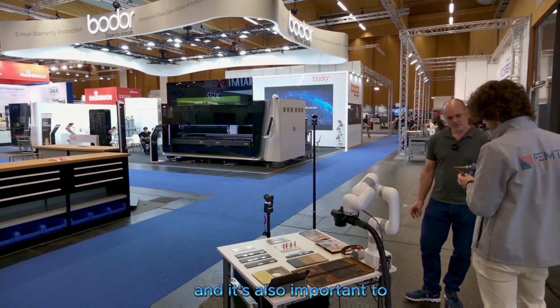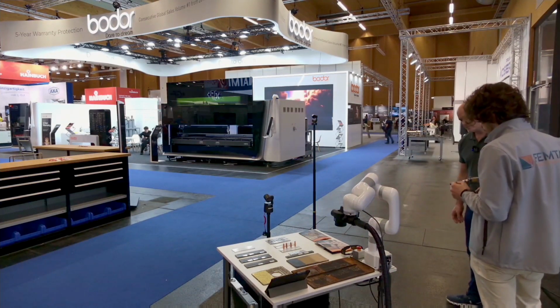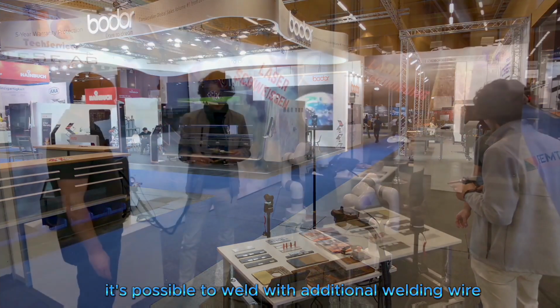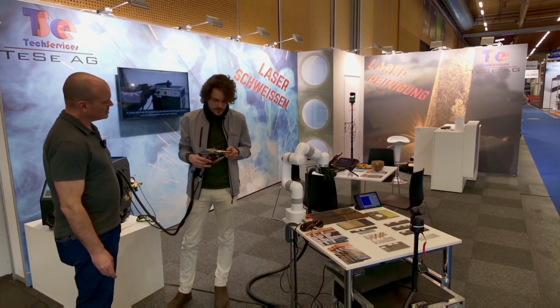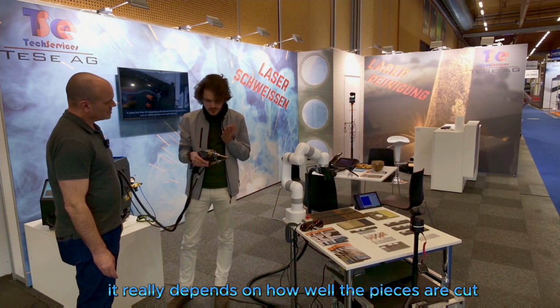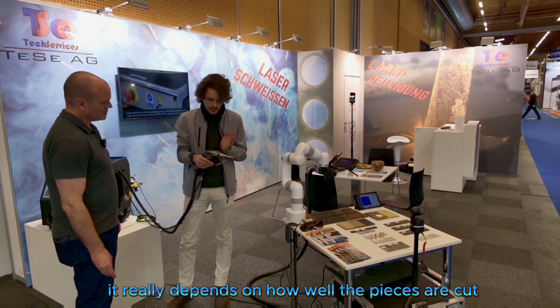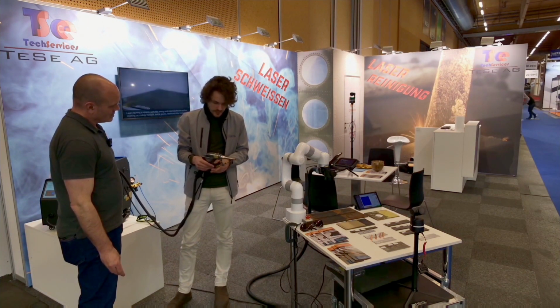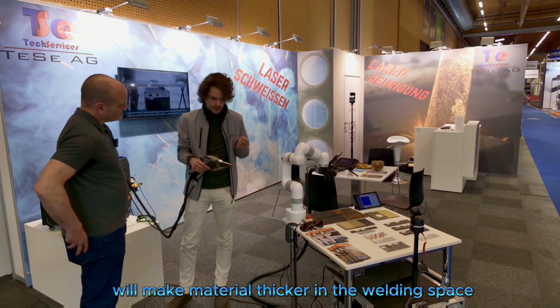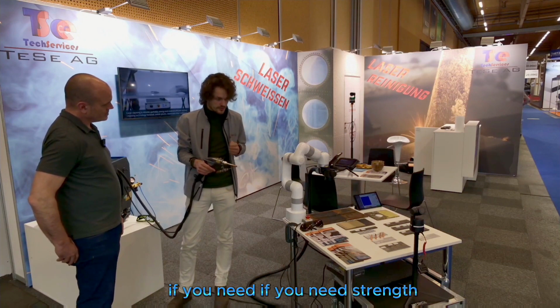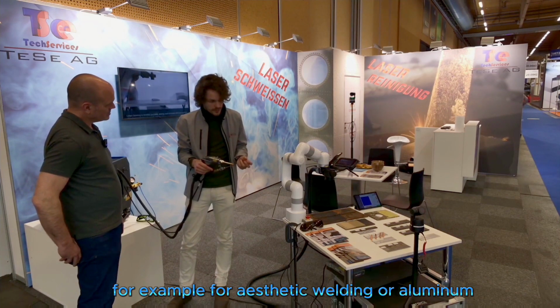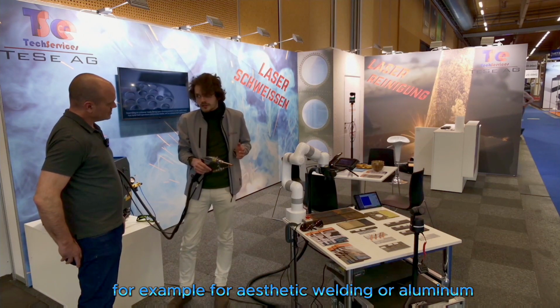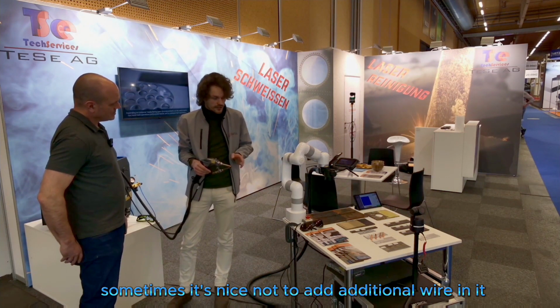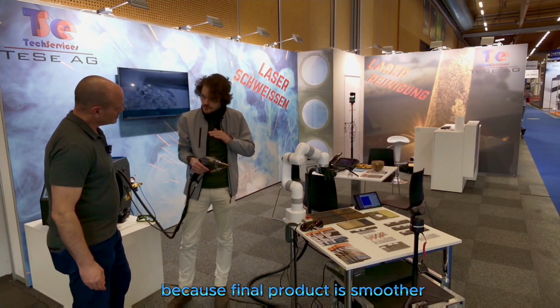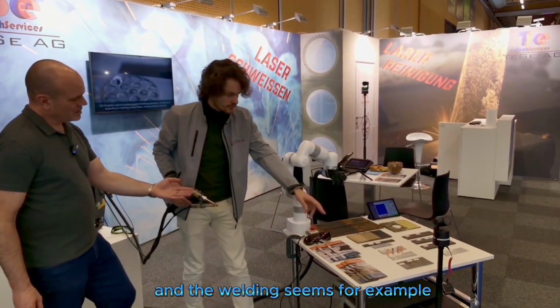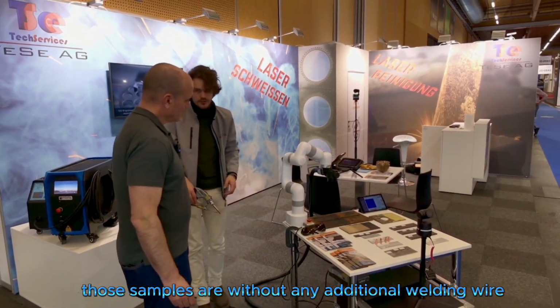And it's also important to say that it's possible to weld with additional welding wire, but also without additional welding wire. And the results sometimes can be better with or without. It really depends on how well the pieces are cut and how well they fit. In most cases, using welding wire, of course, will make the material thicker in the welding space if you need strength. But for example, for aesthetic welding or aluminum, sometimes it's nice not to add additional wire because the final product is smoother. And the welding seams, for example, in those samples are without any additional welding wire.